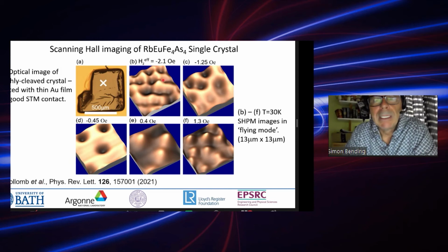And what you can take away from this is that the vortex patterns are actually quite disordered. Certainly we don't see a perfect Abrikosov vortex lattice here, and that's very characteristic of a strong pinning type 2 superconducting material that we're dealing with here. So what we want to do then is generate a rather dilute system of vortices so that no two vortices are interacting. There's very little overlap between the fields of the two vortices. That's what we've done here by cooling in a field of minus 0.8 Oersted, where you can see now these two vortices are quite a long way apart and not really interacting.